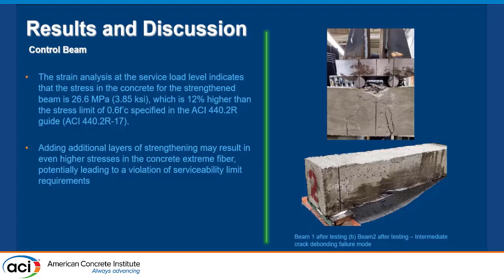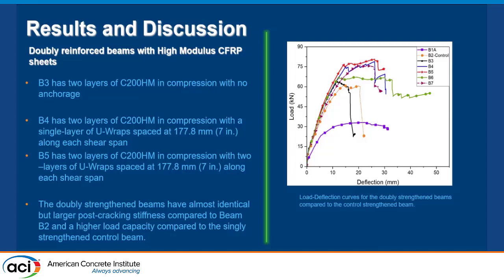So it was like 12% higher, and then we are expecting that adding more layers at the tension and even anchoring that FRP sheet will increase the ultimate capacity, which will increase the ultimate strain and the strain in the concrete. So while we are using more strengthening material, we are violating that limit, that percentage. So here's the idea.